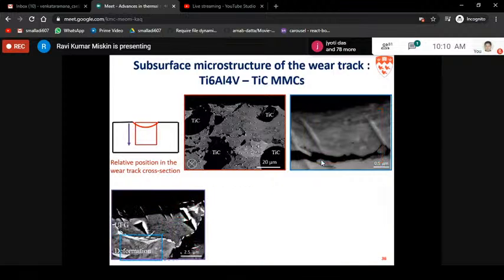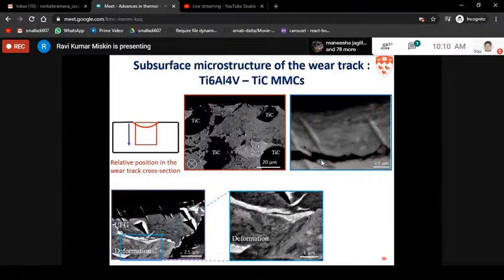Yeah. Below the wear track, you could have some amount of deformation because some kind of stress might go, but you don't see sharp changes in microstructure itself. Which means that you're actually protecting your subsurface also by forming these types of films. How we concluded this? Next slide.